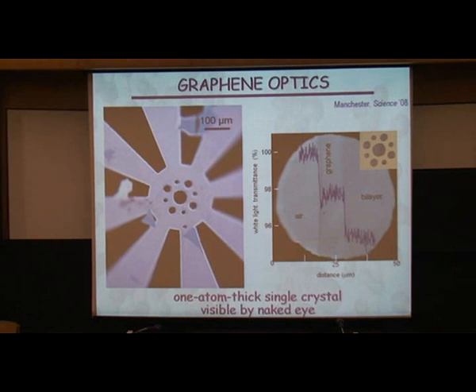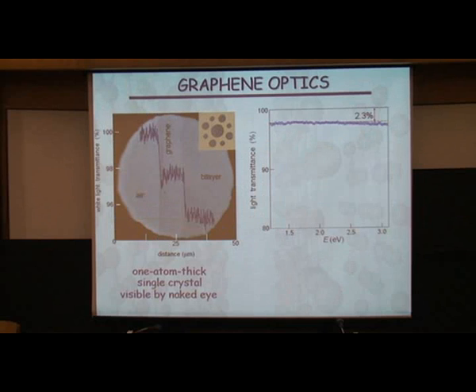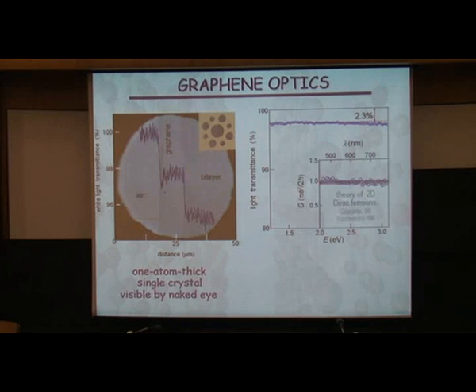Nice to see a single crystal by the naked eye, but what you can do, you can analyze it spectroscopically, and this is our spectroscopic measurement, what's happening, and it's pretty boring, nearly flat spectra for all visible frequencies. 2.3% with very high accuracy and so on. What does 2.3% mean? It's rubbish. This is where theory comes into play. You compare this in terms of Joule losses, say how much light is absorbed as Joule losses, and you can deduce the conductivity of this material at optical frequencies.